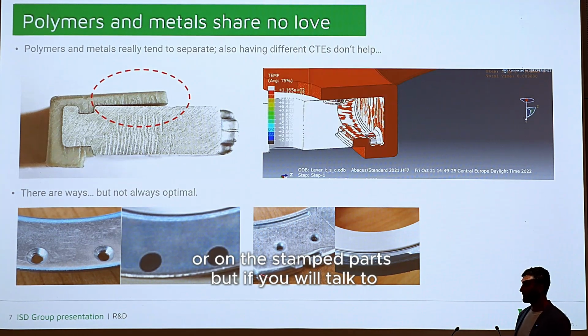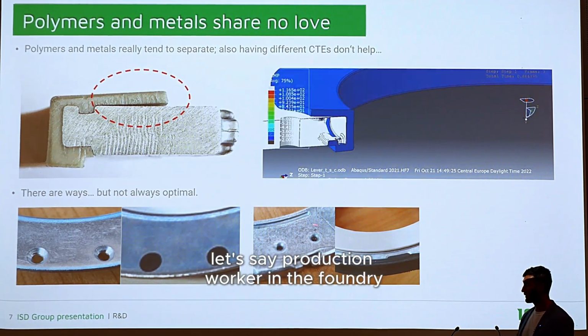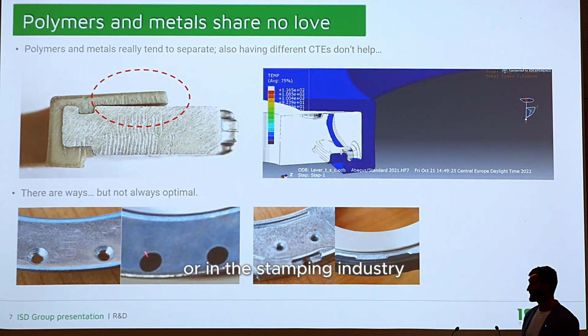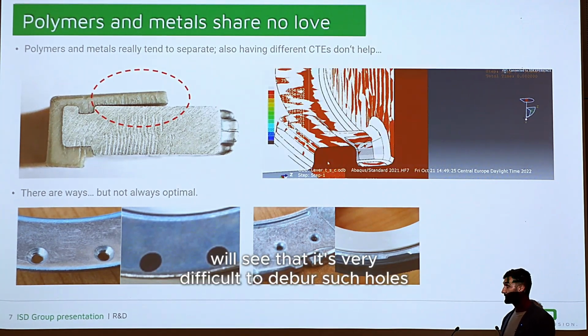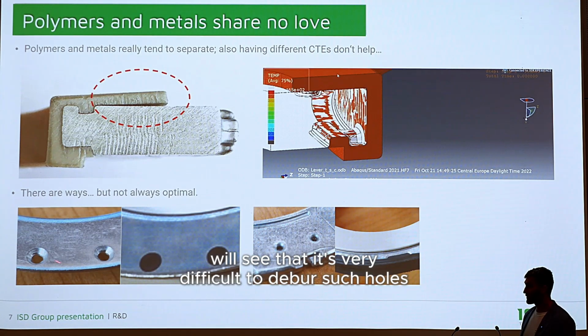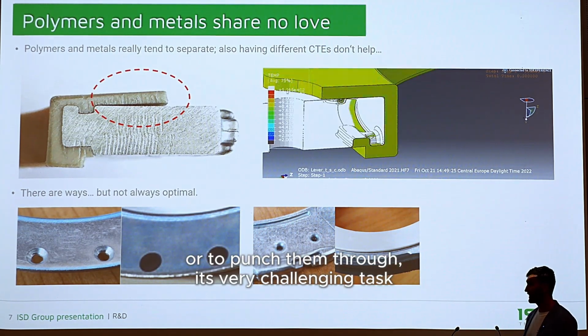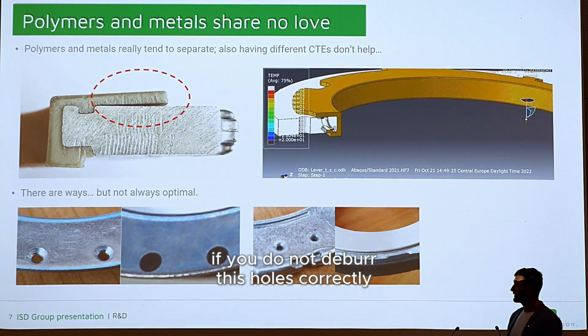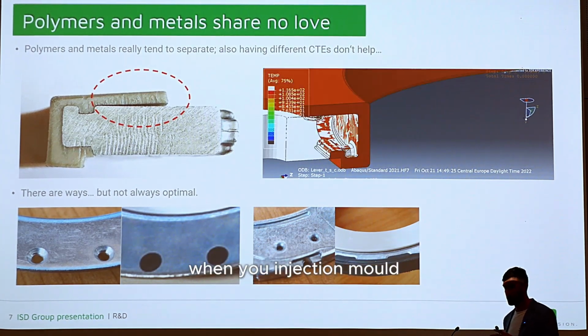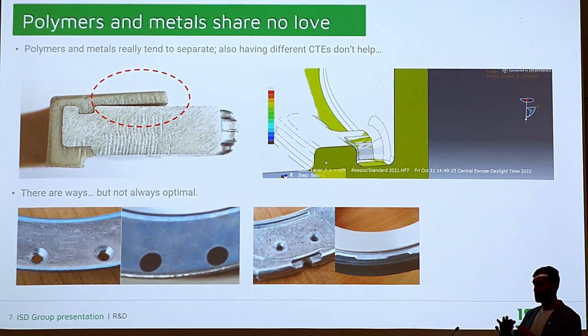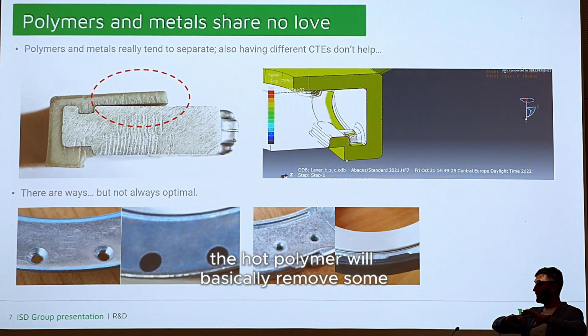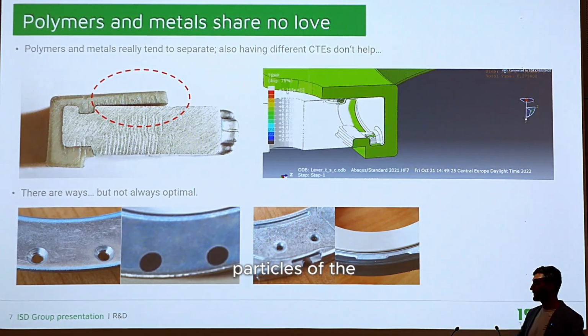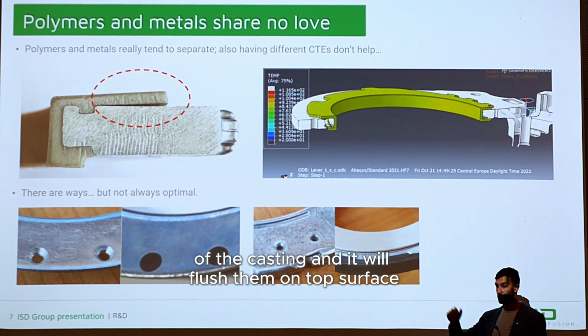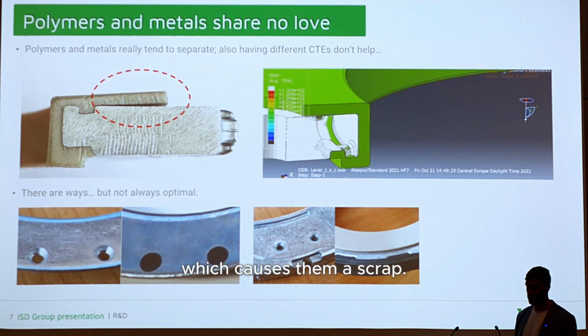But if you talk to a production worker in the foundry or in the stamping industry, you will see that it's very difficult to deburr such holes or to punch them through. It's a very challenging task. If you do not deburr these holes correctly, when you injection mold the polymer inside, the hot polymer will remove some particles of the casting and flush them on the top surface, which then causes scrap.